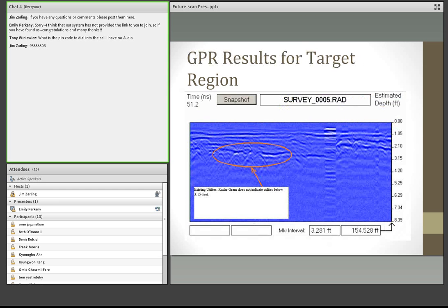The next slide that I'm going to show you are the GPR results for the target region. Unfortunately, the GPR did not work at all. What we suspect happened was that there were already some installed utilities over top but below of the ground surface in the area where the pipe was installed.